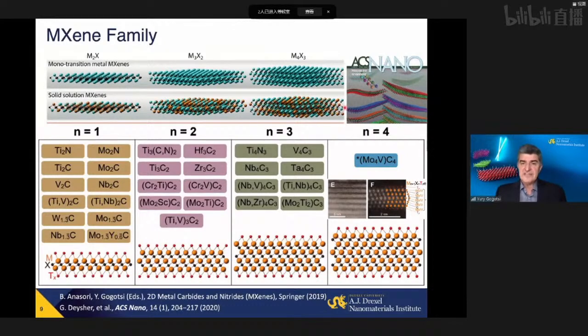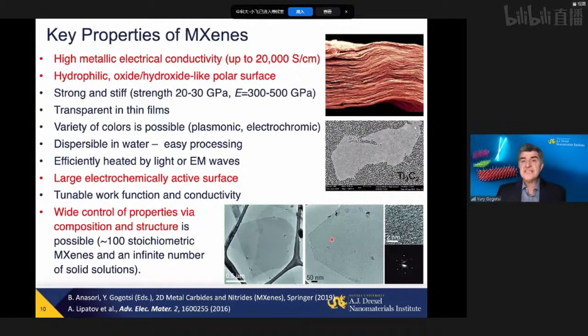So we basically have a material which is conducting like a metal. And keep in mind, graphene is even a zero band gap semiconductor, but these materials have a high density of states at the Fermi level. And at the same time, the surface looks like a surface oxide or hydroxide. So you can run the same, say, electrochemical reactions as with oxides. And they can have conductivity 3 orders of magnitude higher than activated carbon used in supercapacitors, or at least an order of magnitude higher than, say, reduced graphene oxide. It's very important, again, for high power applications. But these oxide-like surfaces also give easy processability from aqueous solutions, and they are electrochemically active.